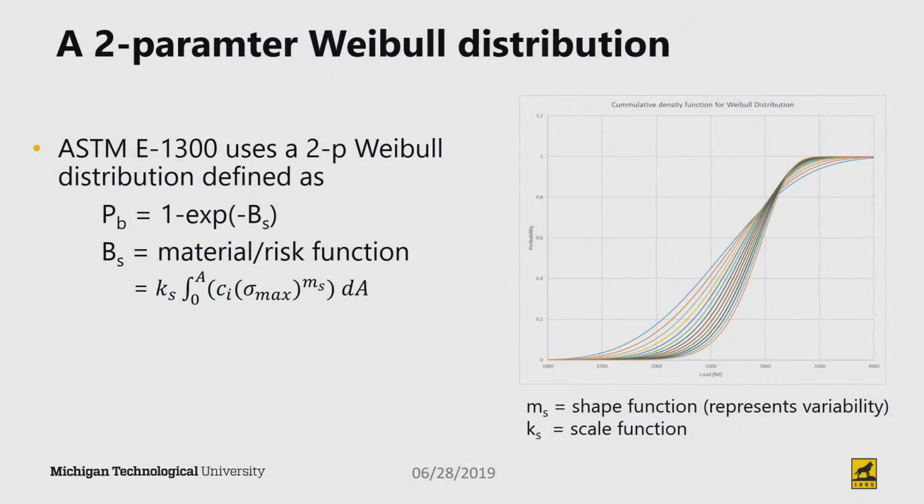The glass failure prediction model is principally based on a Weibull distribution, and the key thing to recognize is that the risk function used in the model is different from the base one that is part of the Weibull distribution. We've added some pieces to account for area effects.